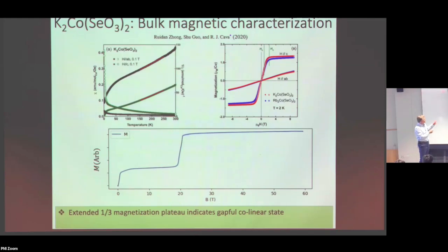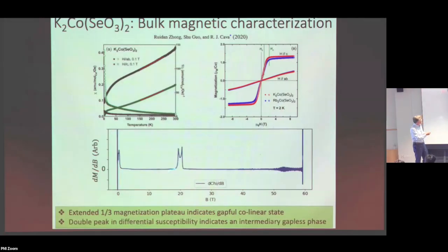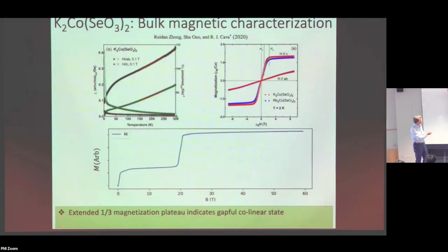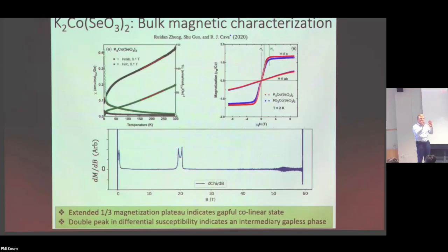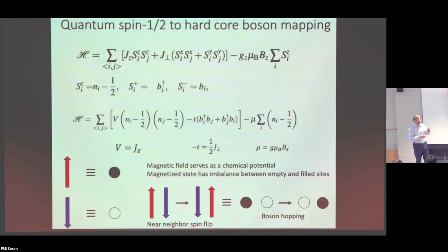Now, if you look at dM/dB, the differential susceptibility, which is what you measure more directly in the experiment, then you see that this transition actually has 2 little spikes to it. That was fantastic to see. And we'll get back to that in a little bit, because we think that what's between these 2 spikes is a supersolid state that has both density modulation as well as a superfluid component. And we'll get around to how that becomes connected to a spin system.